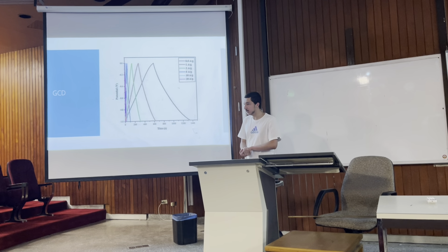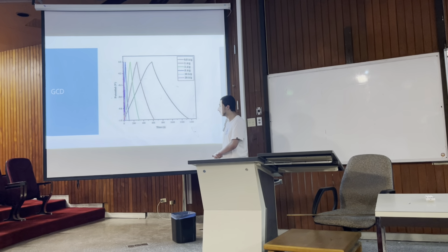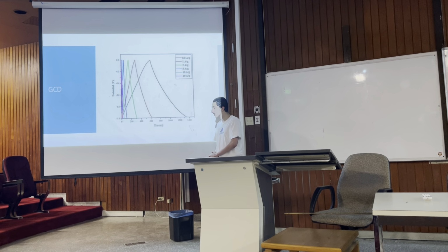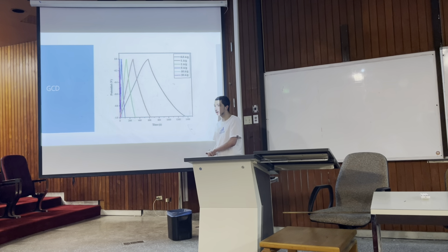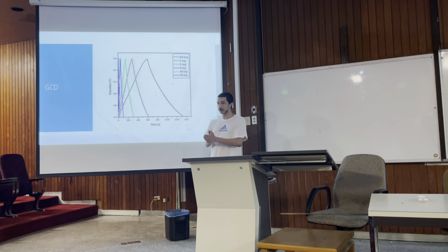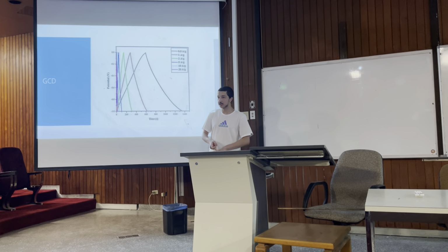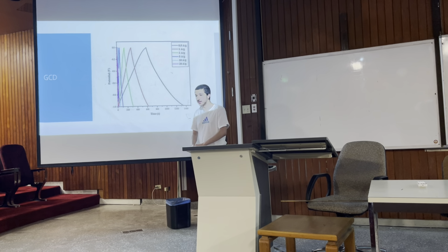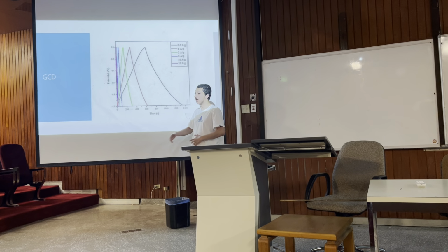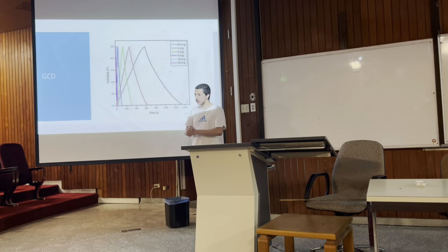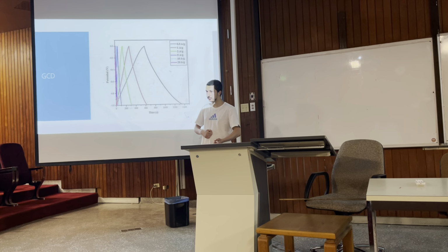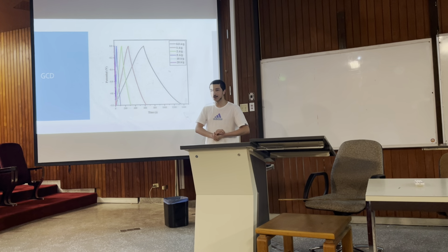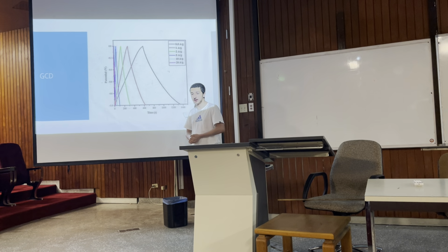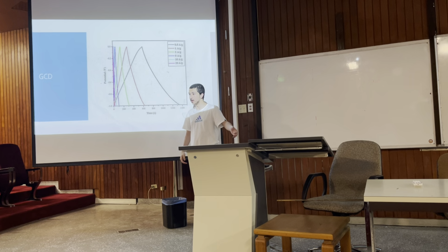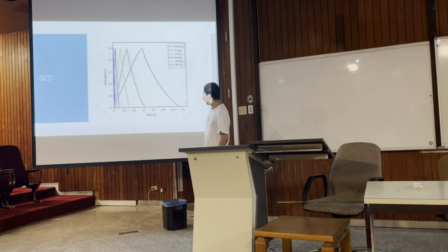We also have GCD, galvanostatic charge-discharge, which measures another strength of the supercapacitor. The supercapacitor has two main strengths. The first is that we can attain very high capacitance through it. The other is that it can give us very quick charge-discharge times, which is why it's imagined to be a good alternative to batteries. How quick is quick? You have hundreds of seconds.